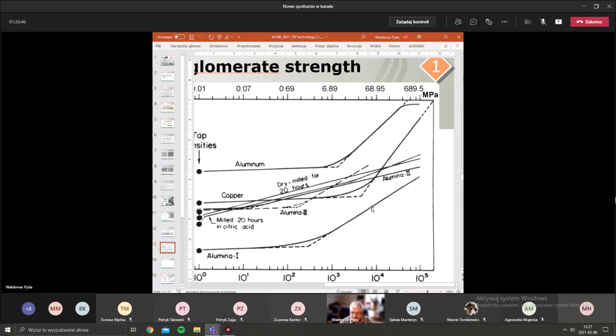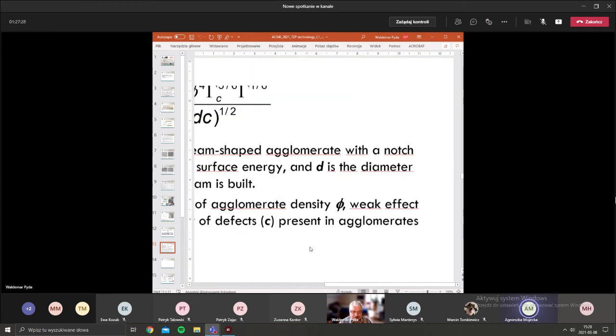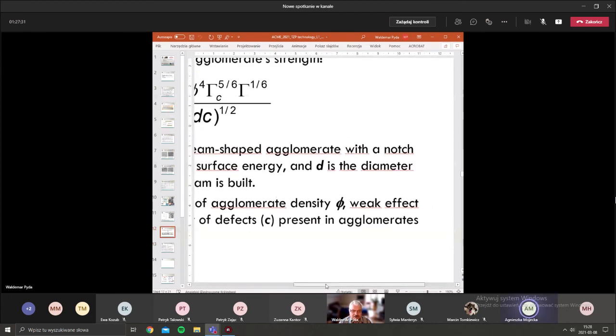At higher pressures, granules were damaged, and the microstructure is very uniform. This breaking point is a measure of what, Agnieszka? The pressure which corresponds to the breaking point in this curve can be attributed as the strength of agglomerate. The strength of agglomerate.